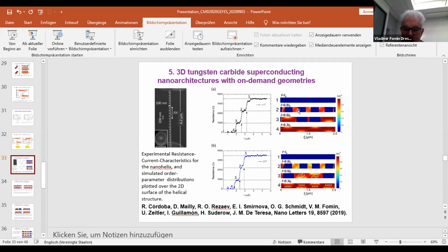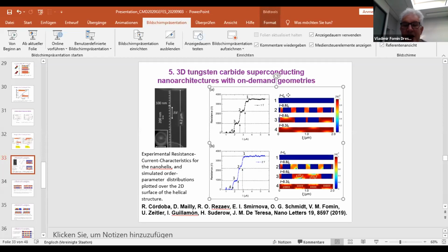If we further increase the transport current, these phase slips develop in more extensive regions, practically in all windings, but there are still some regions where the magnetic field is tangential to the nanohelix, and therefore we arrive at the second shelf. And at still higher current, practically the whole nanohelix is already normal, and we have the finish of this superconductor to normal transition.